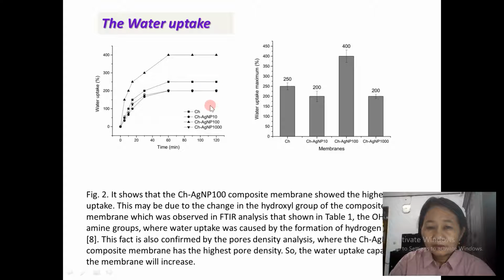And based on this result, we can calculate the maximum water uptake of each membrane, and we got that the S2 membrane has the highest maximum water uptake. Okay.